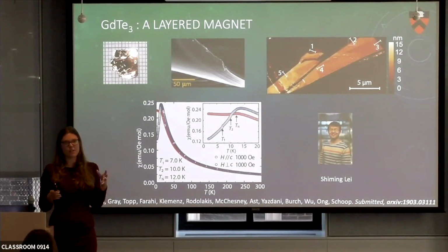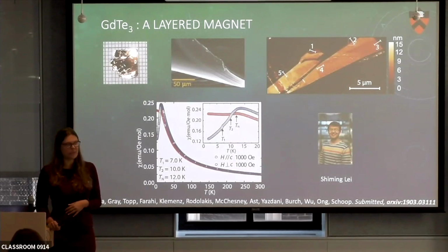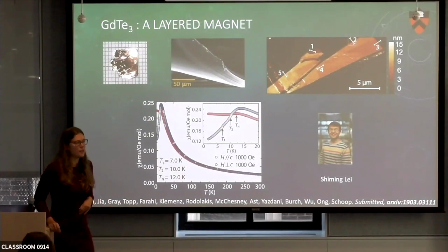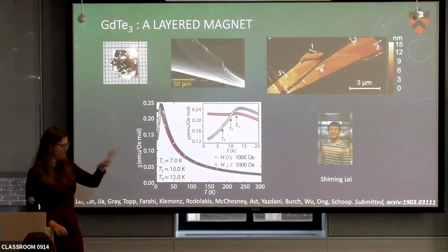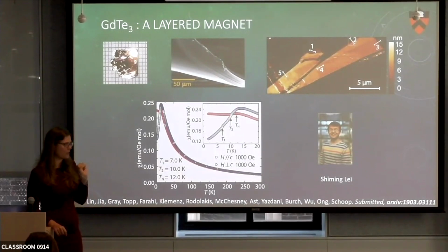And I know that there's a discussion of what comes first, the charge order or the structural order. I personally believe that it's always a structural effect. There's a big difference between structural transitions and charge density waves, right? I mean, for example, all the AC conductivity, sliding motions, and so on, these are clearly itinerant phenomena that you will not get from a trivial structural distortion. Okay, yeah, so I definitely have to do more reading, but this is just my general thing: all the materials I studied that are charge density waves in the literature are structurally unstable. So therefore, for me, this is kind of synonymous in the literature, but I just started digging into the charge density.